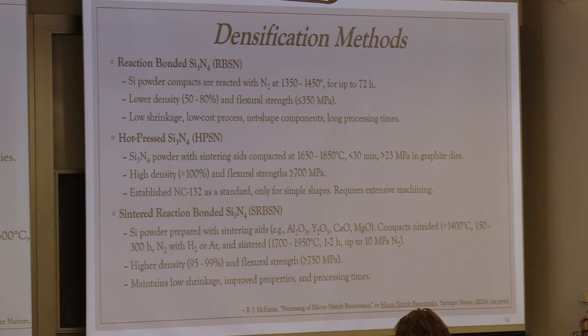The next method that came up was sintered reaction-bonded silicon nitride. The sintered reaction-bonded process is a takeoff from reaction bonding, except this time you mix sintering aids into the silicon powder, react it to form silicon nitride, and then take it up to much higher temperatures to actually densify the material. This proved to be very effective in increasing the strength and density of the materials, and it allowed you to produce complex shapes. I will say that Kyocera has, I think, perfected this particular process for some of their devices.